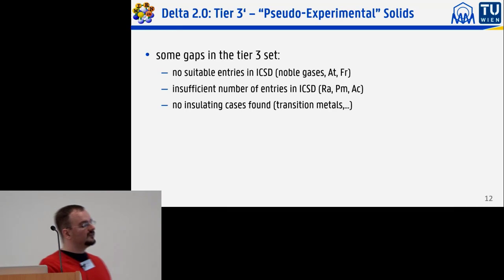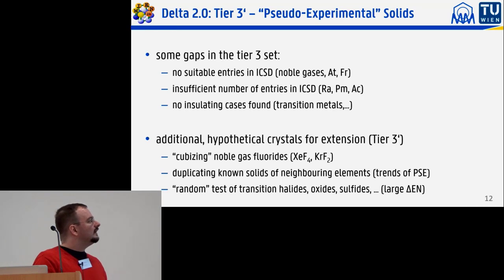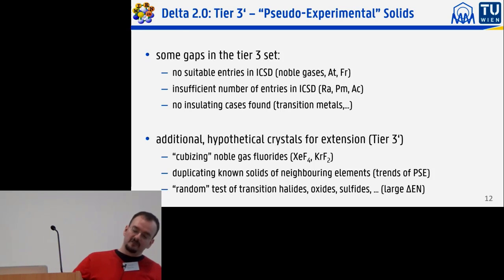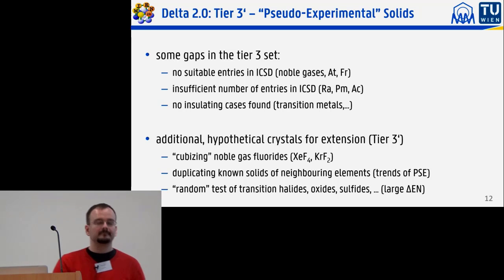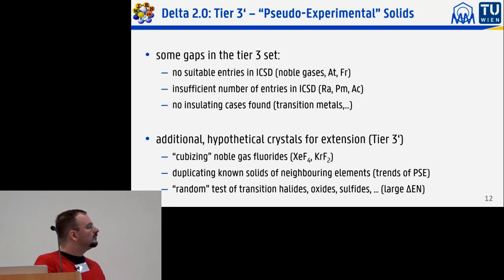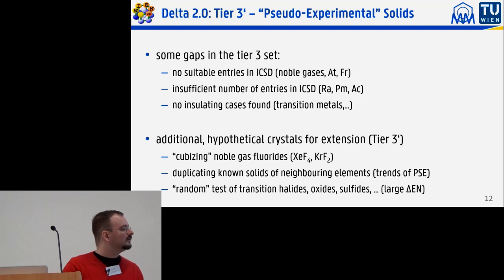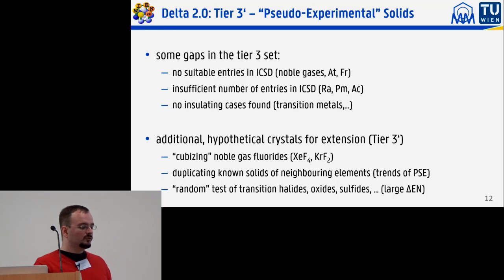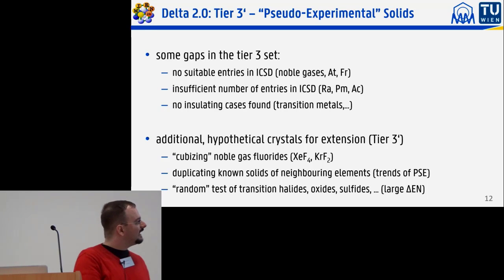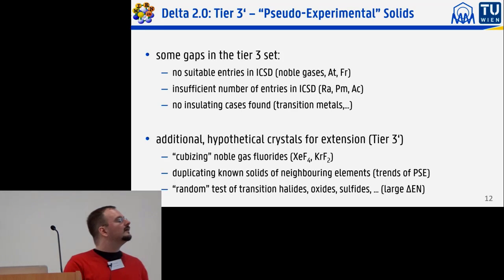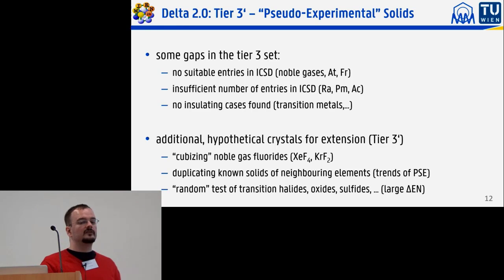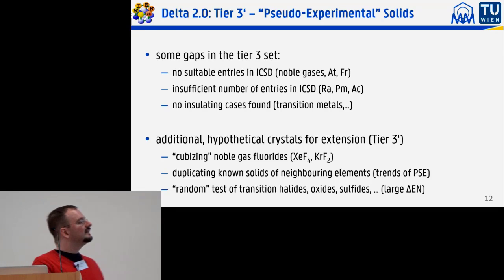There are still gaps, so I am currently working on an extension called Tier 3 prime, which aims to fill them in two steps already completed with a third underway. We took experimentally known noble gas compounds — xenon tetrafluoride (XeF₄) and krypton difluoride (KrF₂) — and placed them in cubic cells, preserving the distances between the noble gas and fluorine atoms.